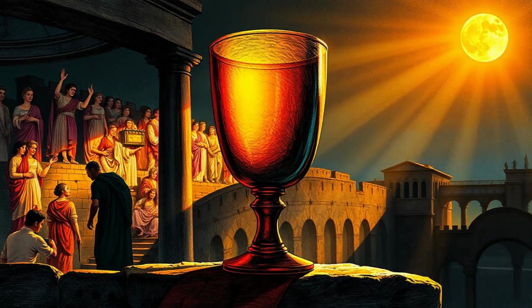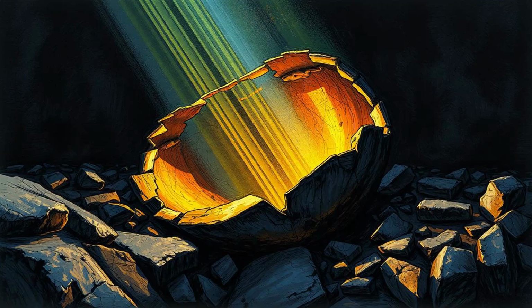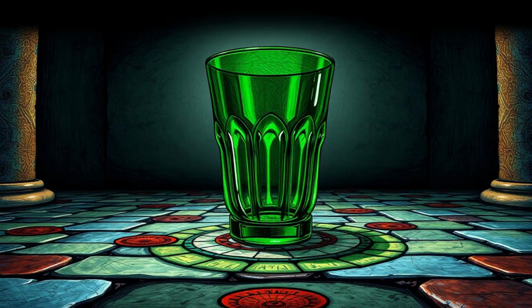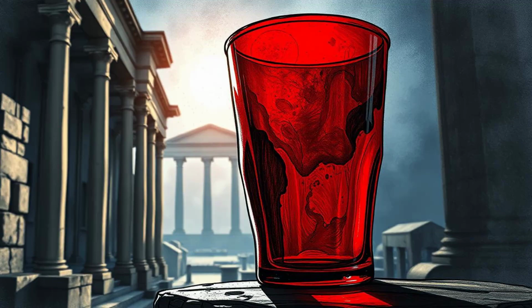It's a phenomenon called dichroism, and it's caused by the way these tiny metal nanoparticles interact with light. When light hits the cup, the electrons in the metal particles vibrate. The way they vibrate depends on the size of the particles and the direction of the light. When light is reflected off the surface viewing from the front, the particles scatter the light in a way that makes the glass appear green. But when light passes through the glass viewing from the back, the particles absorb certain wavelengths and transmit others, making the glass appear red. The Romans were practicing nanotechnology 1,600 years before the term was even invented.